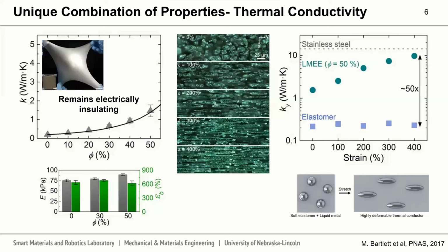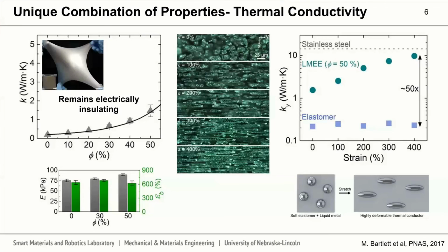Okay, and then another question, does the liquid metal have a max allowable temperature, and does that differ from the elastomer? That's a really great question. The max temperature of some of the polymers we're using is a few hundred degrees Celsius, probably 250 to 300 degrees Celsius. The max temperature of the liquid metal is in the thousands of degrees Celsius, so it's beyond most of the polymers that we use.